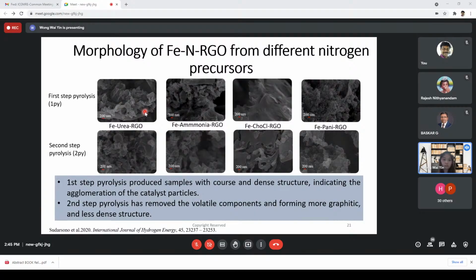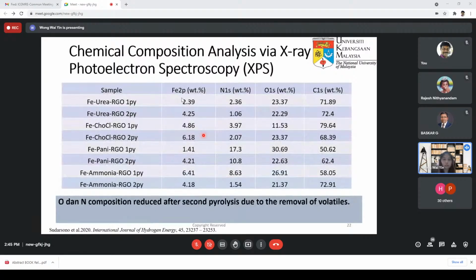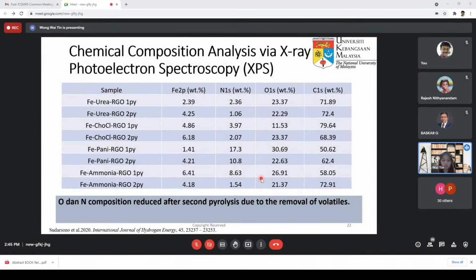We can see that the first pyrolysis has produced samples with a coarse and dense structure, indicating the agglomeration of the catalyst particles. But upon the second step pyrolysis, we can see a less dense structure is formed, and they are more graphitic. Okay, this is simply because the second step pyrolysis has removed the volatile components. If you look into the chemical composition, we can see that the nitrogen and oxygen content after second pyrolysis has reduced. Most of it has reduced. So because, as mentioned, it removed the volatiles, but the Fe still remains as it's not removed at that temperature, and thus it's slightly higher.